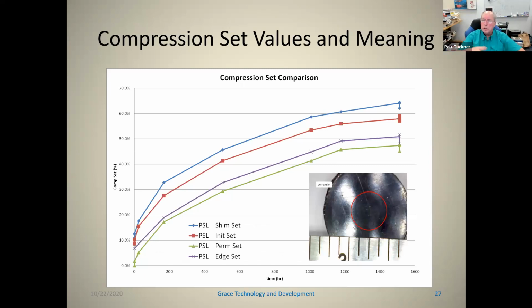So what you can do is you can do this at the end of the test, but if you want, you can add additional jigs and take them off test at different intervals. And when you do that, you can see the progression of all 4 of the different compression set values, along with the CSR testing you do, because you'll have more additional values.